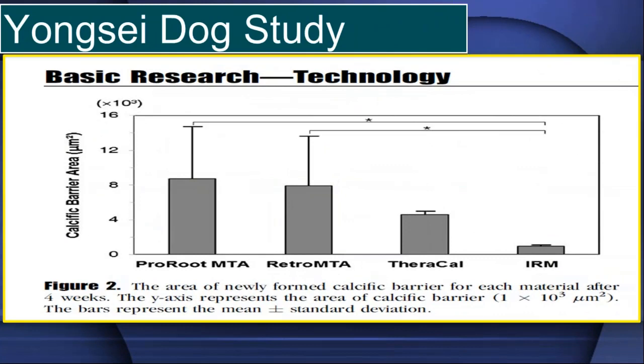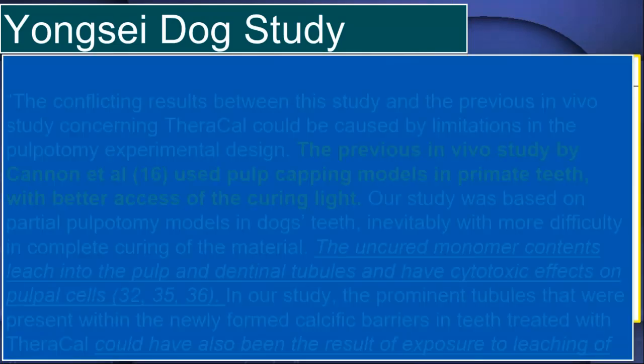And this is really bad because of those tall pulp horns they went into. They went all the way down to make a pulpotomy, and they still had those tall cusps. And they even said it too, and I'll show that to you, that their results aren't bad for Theracal LC. It was supposed to be Theracal PT. It would have been a lot better because it would have dual cured, much better than IRM, as you can see there. Much better than the control IRM, but not as good as ProRoot MTA or Retro MTA, which is their product. And this is what they said.